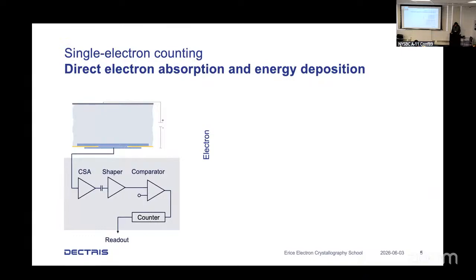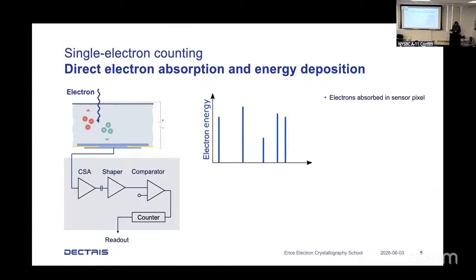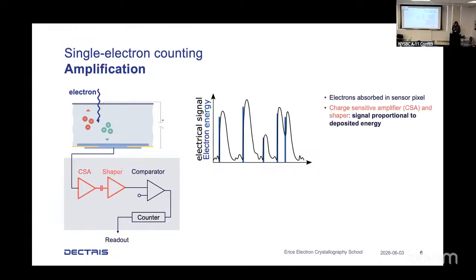How they work is illustrated here. When an electron is stopped in the sensor, it releases electron hole pairs, and the amount of electron hole pairs is proportional to the energy deposited. For each 3.6 electron volts, you get an electron hole pair. We apply a reverse bias, and this makes the charges drift to a charge-sensitive amplifier, followed by a shaper stage.